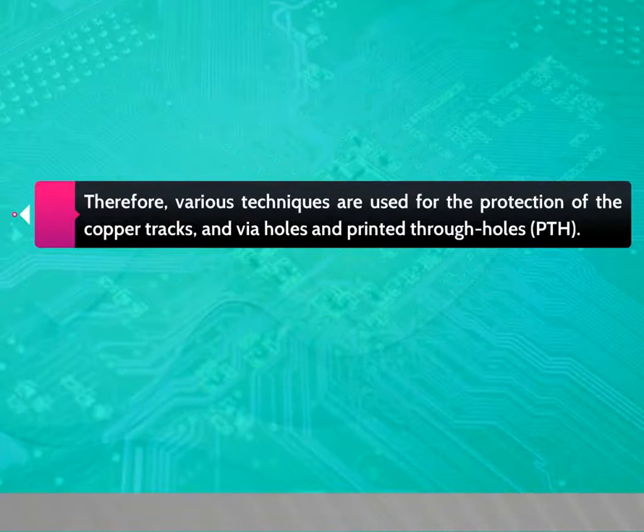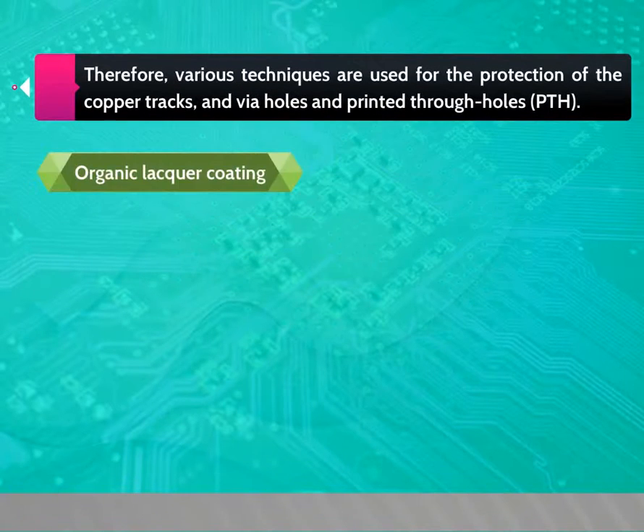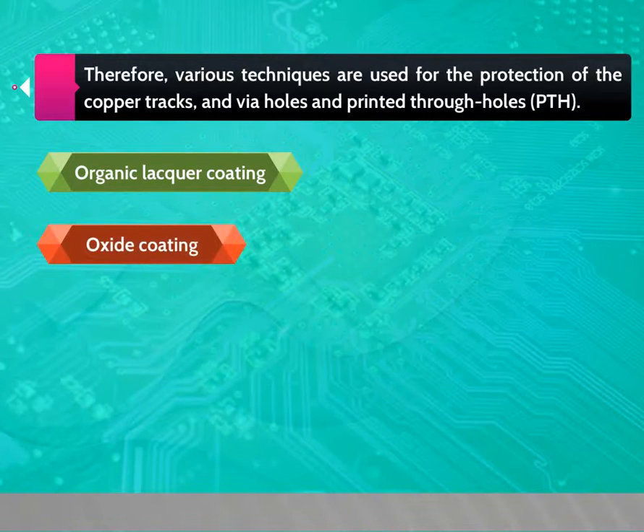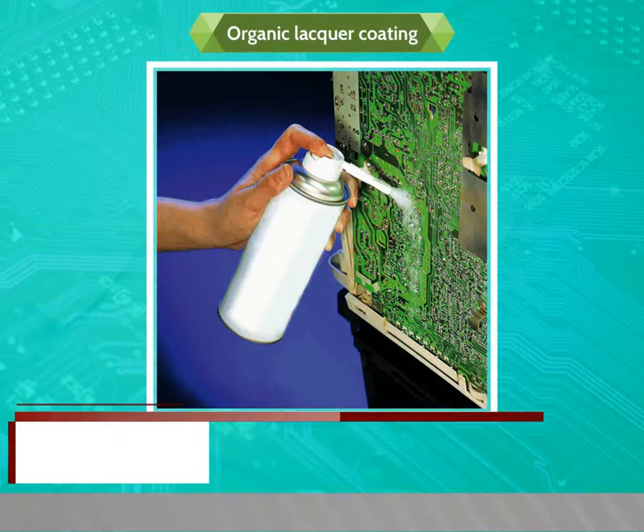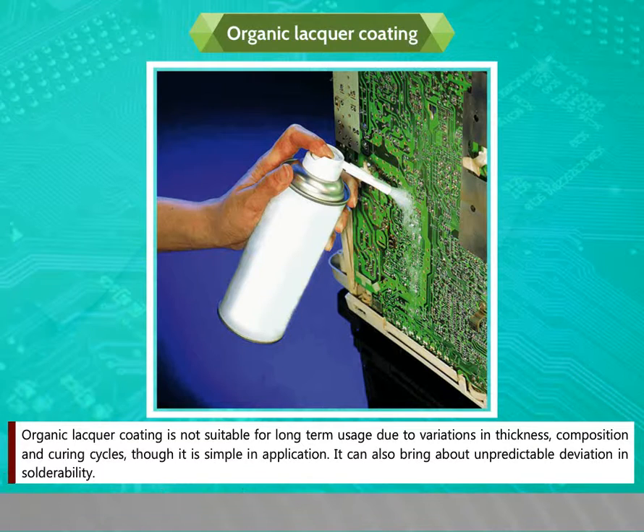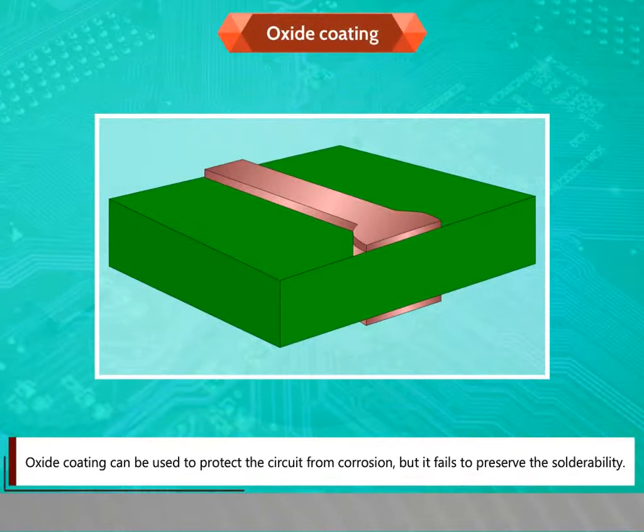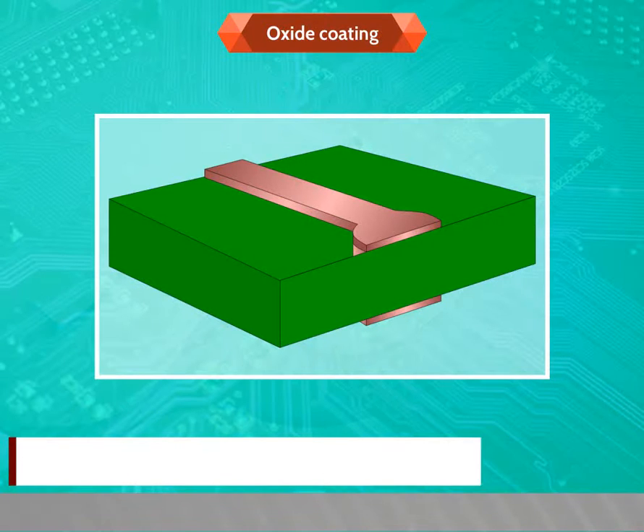Therefore, various techniques are used for the protection of the copper tracks and via holes and printed through holes, that is PTH. They are organic lacquer coating, oxide coating, and plating. Organic lacquer coating is not suitable for long-term usage due to variations in thickness, composition and curing cycles. Though it is simple in application, it can also bring about unpredictable deviation in solderability. Oxide coating can be used to protect the circuit from corrosion, but it fails to preserve the solderability.